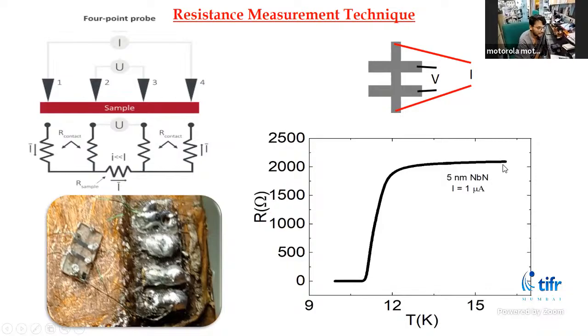You can see here the resistance is going to 0 below a certain temperature. So here one thing is established, that the superconducting film we are growing has zero resistance below some certain temperature. For 5 nanometer NbN, we can see that the TC of that particular sample is around 11 Kelvin. Here I'm showing a photo of our sample, which is in a Hall probe geometry shape, and we measure it in our RT probe that I'll show you later.